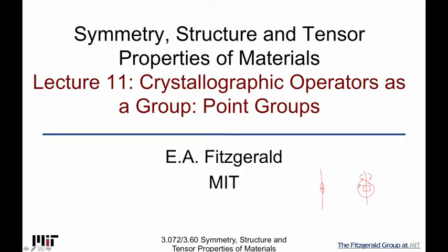That is, these things all have particular symmetries around the particular thing. And remember, it's just operating around this point. We haven't dropped them into a lattice yet, right? So this thing will be called a point group. And we want to develop these symmetries because, of course, in crystals we can have, as you'll find out later, something called a basis, which is a certain number of atoms sitting around a lattice site, and they're reproduced through the crystal structure, and that's how you can think about the geometric equivalent that we're doing here.